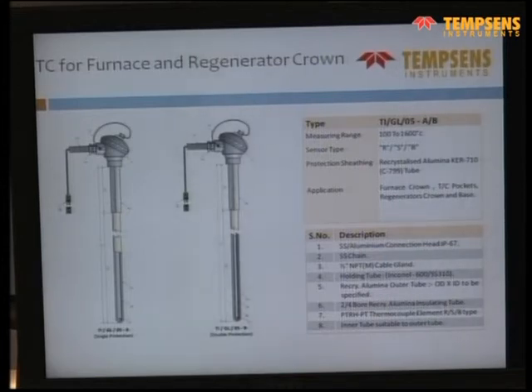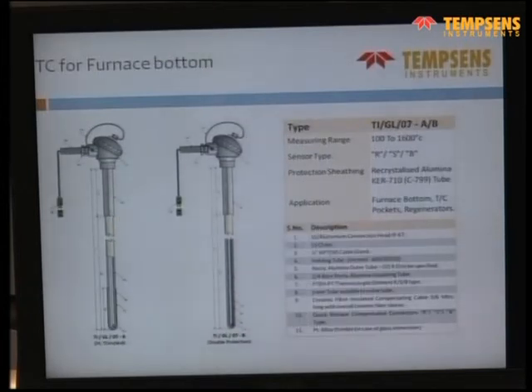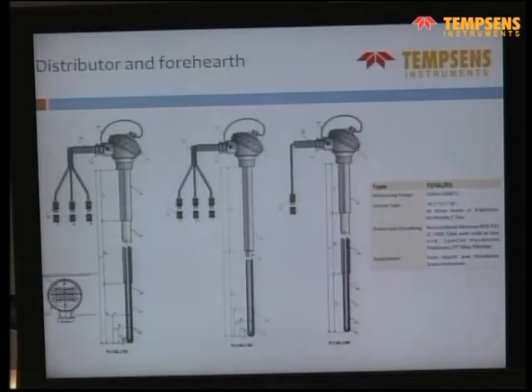So this is for the top of the furnace. This is a double ceramic tube, which is a simple thing, a single or double ceramic tube. At the furnace bottom, sometimes they have only the ceramic, which is inside the refractory itself. It is not touching the glass, but over a period of time, maybe 3 years, 5 years, the refractory will be worn out. So they have a small platinum thimble, a small platinum cover, as you see in the left hand side picture. So even if the refractory is corroded, the thermocouple tip would still be made of platinum, so it will be intact, and the thermocouple will still give the temperature.